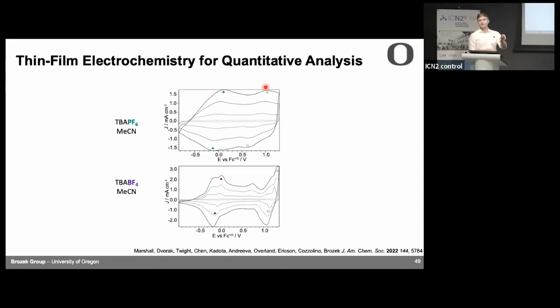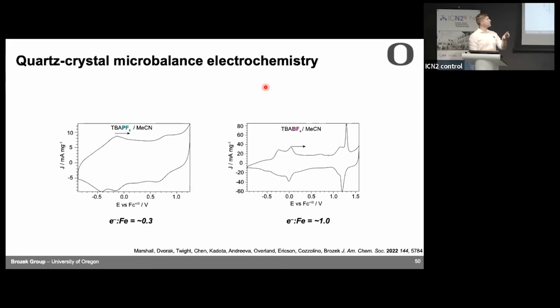Well, we wanted to dig a little bit deeper. And so we used something called a quartz crystal microbalance as our electrode. It's a piece of quartz that resonates at a frequency that depends on how heavy it is. So you can track the mass of your electrode by using a QCM electrode. And so we repeat these experiments. First, I'll just show the current.